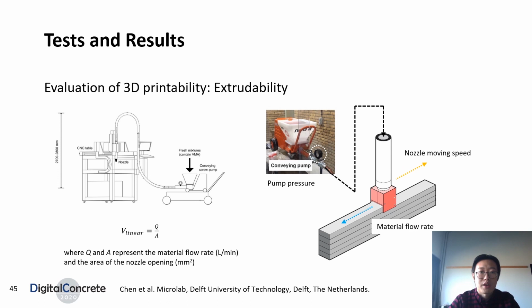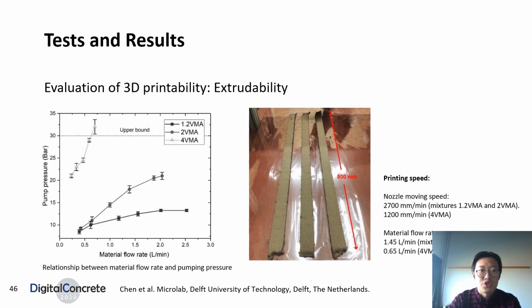The second aspect is about the evaluation of 3D printability. The extrudability test aims to find out the proper material flow rate and nozzle moving speed. We applied different material flow rates and checked the corresponding pump pressure. Mixture 4 VMA shows very high pump pressure and easily reaches the maximum value of the allowed pressure. This also limits the printing speed of mixture 4 VMA.